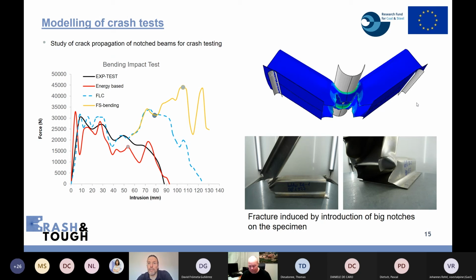To show the advantages, we did the simulation using a conventional FLC. It is the blue line. I don't show a simulation image because the failure position and the fracture morphology are more or less the same as you can see with our model, but the intrusion is bigger and the energy is overestimated. The circular point on the plot shows the moment when the crack starts. And you can see that when you are using the FLC, the cracks start too late.